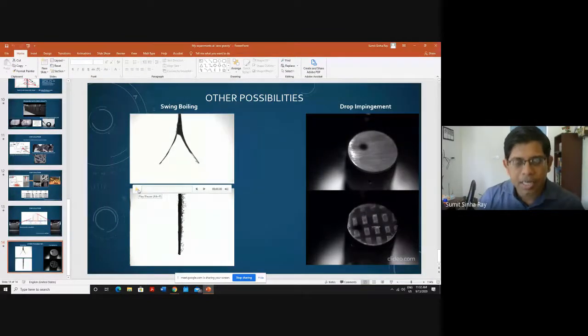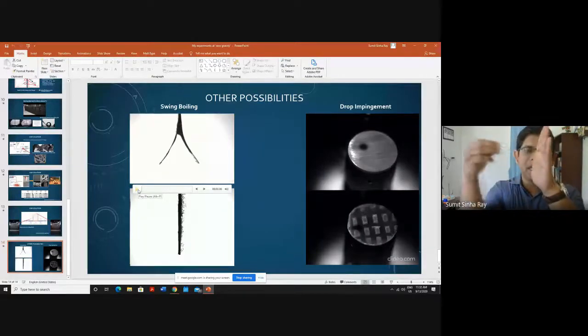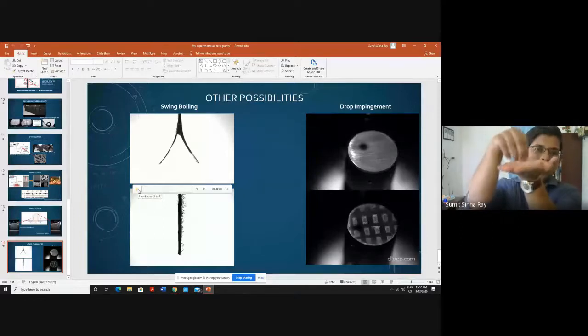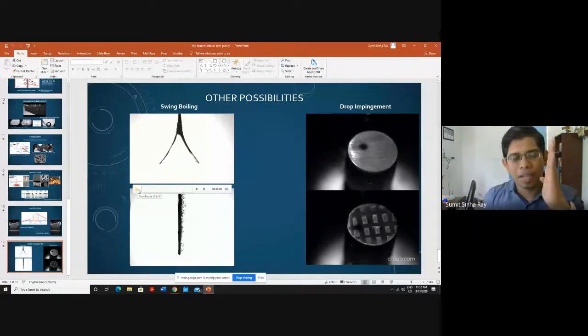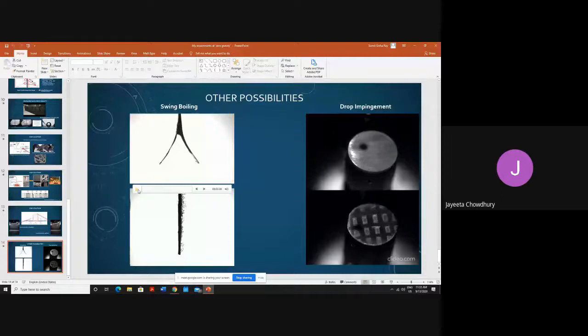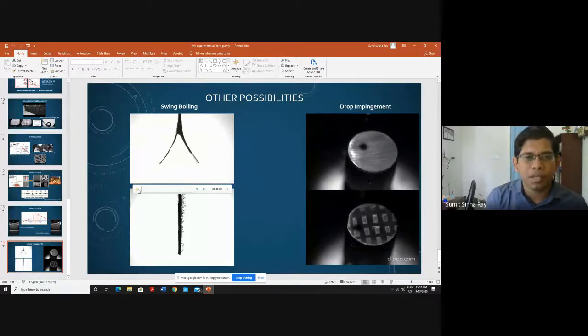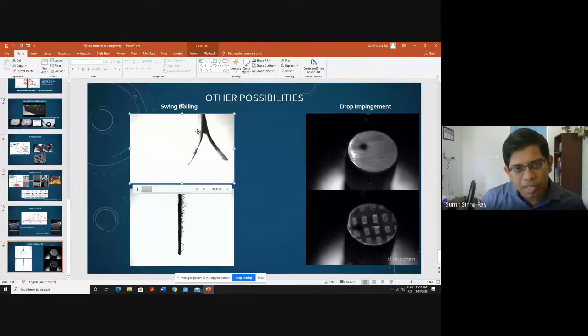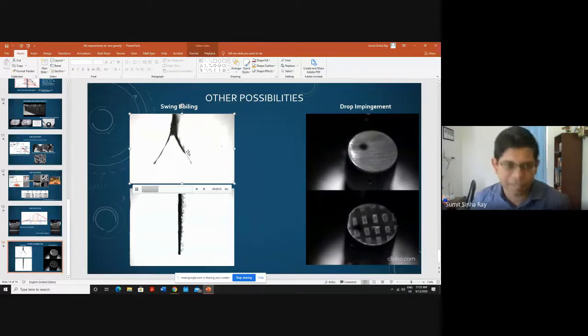Once it was heated, the bubbles leave the surface vertically first and then go up in gravity. If it was like this, they would just go normally up. But if that sample is kept vertically, then the bubble will always leave normal to the surface. Now, as it leaves normal to the surface, all these thousands of bubbles that leave push the surface back. Now, in zero gravity, the condition is that you have to remove the bubble. So what if the surface doesn't stay at its position, the surface tends to move back, and then automatically we end up mixing the liquid. And that is what happened when we were having boiling on this surface, the surface moved to the other side, and vice versa. So this was the underlying phenomenon for this case.